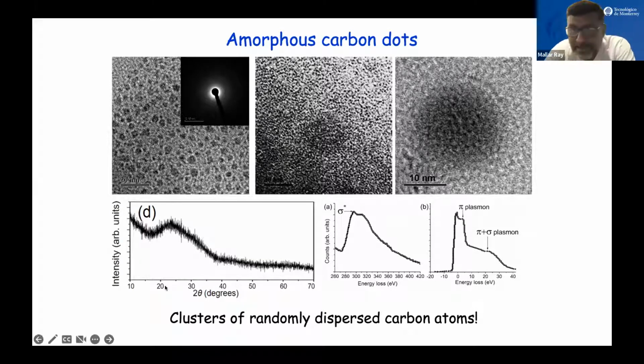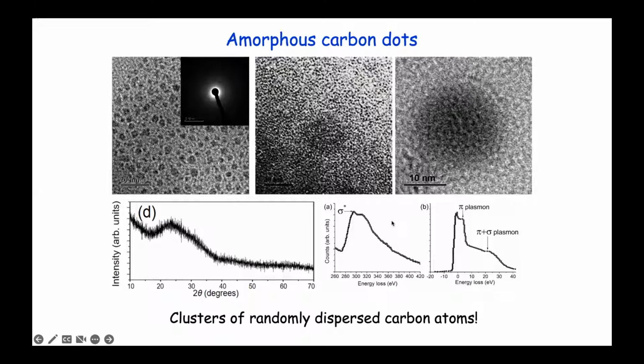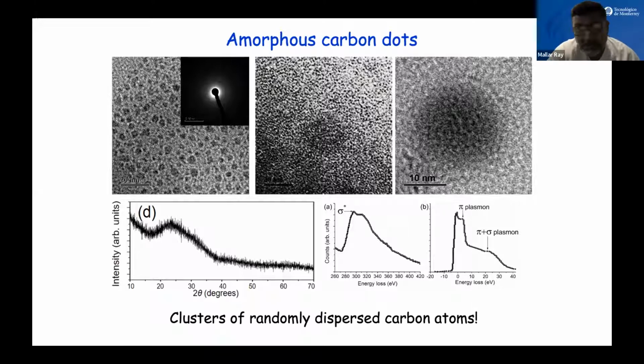But the structures that we made in our laboratory, in a very simple way, I'll go through it, just looking at the image, they look like graphene dots. But every time we tried to get an electron diffraction pattern or looked at the fringes, we failed. But that was not conclusive. So we had to do some other experiments like electron energy loss spectroscopy, which can show some signature peaks of crystalline order. But all these attempts, we failed. We never found any crystalline order in any of these structures that we made, which forced us to conclude that these are a random arrangement of clusters of carbon atoms, which are kind of caged maybe by some surface